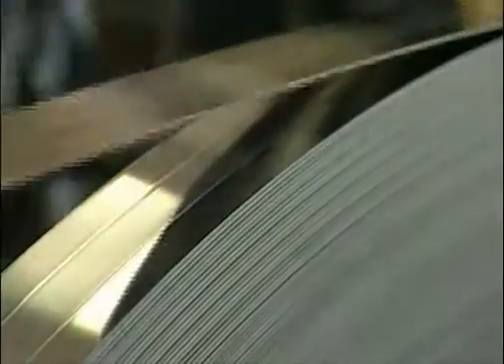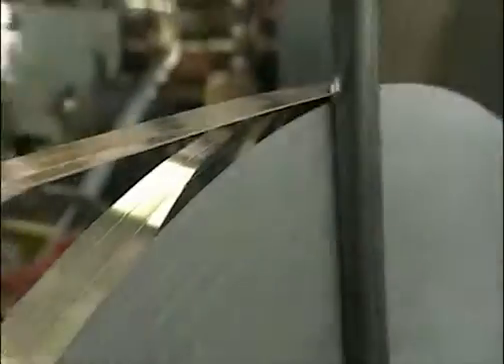The edges of this thin strip are going to be welded to the edges of two others by electron beam welding. This type of welding was chosen because the heating is so localized that distortion cannot occur. Neither can heat tinting. The welding is done in a vacuum.